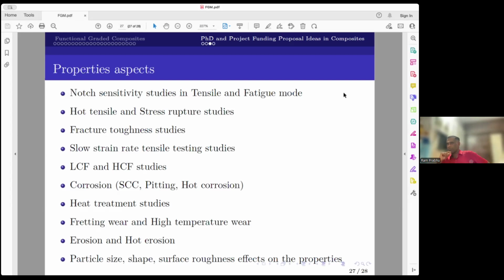And all of your tensile testing, if you do as per ASTM E8, there is a 10 power minus 3 per second strain rate you do it. Have you ever studied the behavior at much slower strain rate or the higher strain rate? And if you look at the data, higher the strain rate, higher the strength, lower the ductility. Slower the strain rate, some material behaves phenomenal ductility. That's what the people call as superplasticity.